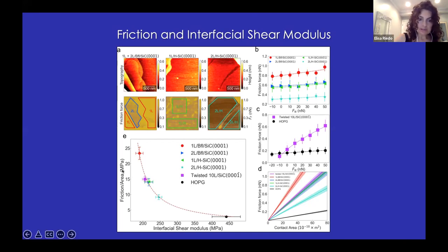And then we plotted the friction per unit contact area as a function of the measured interfacial shear modulus for all the materials measured. And with a very nice surprise, they were all sitting on top of the same general curve. And this is a simple reciprocal curve. It is general for all the different materials.